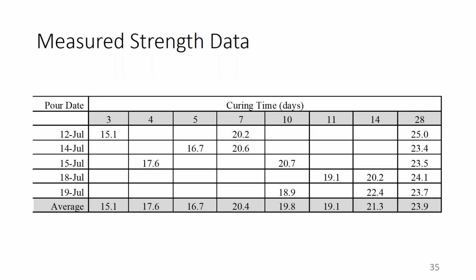Now, after the casting was done, we were taking samples, and Bill and his team were doing that. These were sent out to another third party for testing. In this case, this is the curing time in days, and on the bottom are the strengths we achieved. If you look to the very left, after 3 days, you get about 15 KSI. So it strengthens very quickly, and then it slows down. After a week, you get about 20 KSI, and it remains steady for a while. By 28 days, it had reached about 24 KSI. So that is more than what we assumed. It's a little bit less than what we had achieved in the lab, and that is understandable.